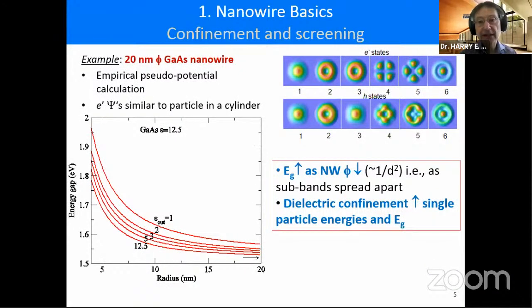Now, I mentioned properties, so very briefly, when you have structures that are within or smaller than the de Broglie wavelength, then you get quantization. You can see the standard states. If you imagine these wires are sitting in a vacuum, for example, well, then there's a hard wall potential. So you get very standard wave functions as shown on the top right. And for, say, gallium arsenide nanowires, you'd have a band structure you could predict, and it would be exactly as you would observe, with approximately 1 over d squared dependence, or radius or diameter dependence, for the band gap.